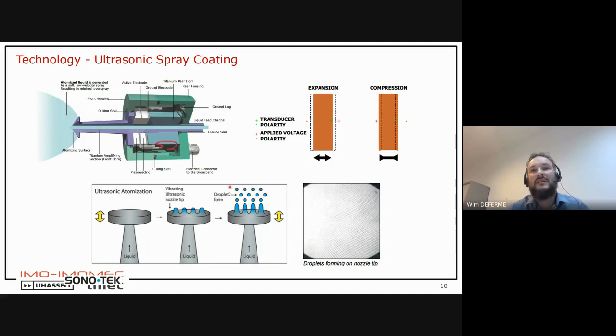So like I said, if you have this way of generating droplets, these droplets have nearly no kinetic energy, but the benefit of it is that these droplets all have more or less the same size, in the order of 20 micrometers in our case. So using this 120 kilohertz, we range around 20 micrometers.